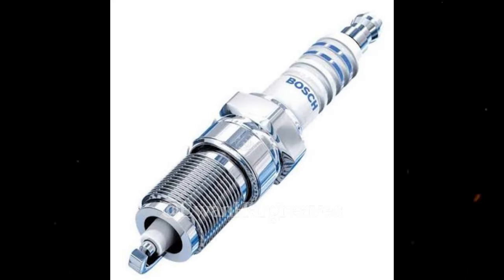That ceramic insulator has to survive conditions that would destroy most materials: 4,500 degrees Fahrenheit, 2,000 pounds of pressure, 18,000 volts of electricity, corrosive combustion gases, thermal cycling from below freezing to full operating temperature hundreds of times a week. And it has to do this for 50,000, 100,000, even 150,000 miles without failing.